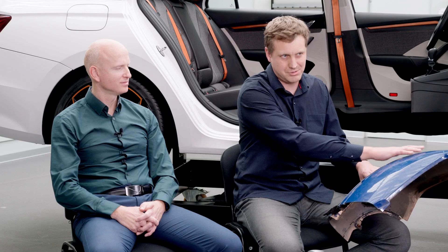Now let's talk about the specific projects. You recently revealed the Bumper to Bumper project — that means you are able to recycle material from discarded bumpers of old cars from scrapyards into new bumpers that can be used on a car. It may not just be specific Škoda bumpers but also other brands, because bumpers have a big advantage: the main load-bearing part is polypropylene, and all car companies use the same material and concept for these big parts. So it's possible to use bumpers from all brands.